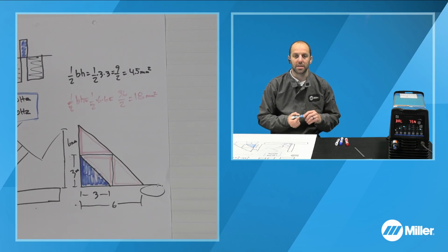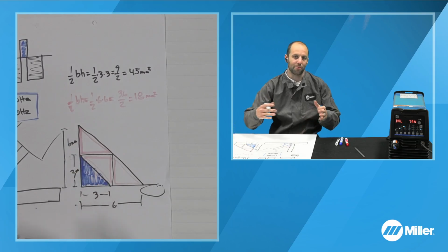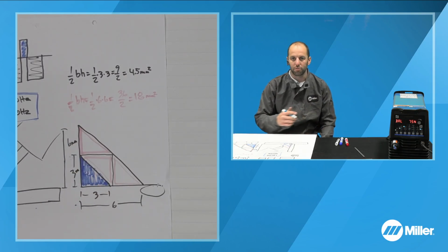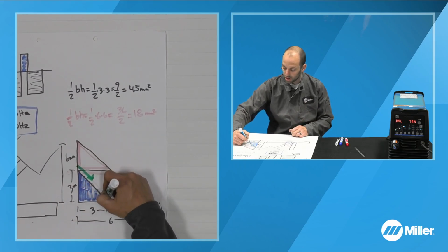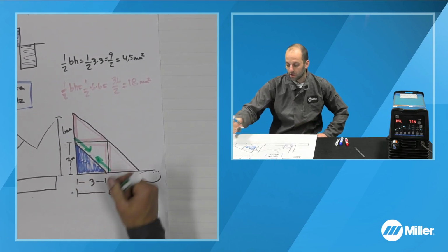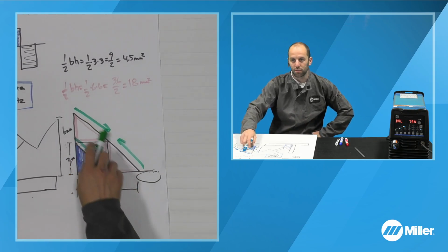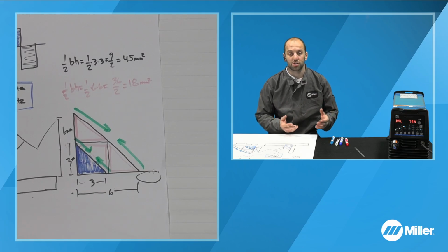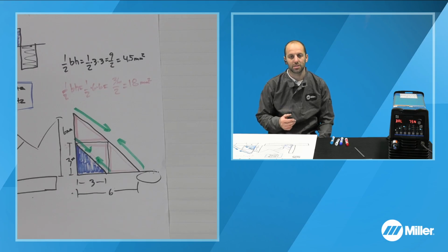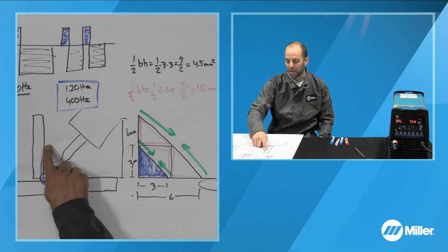The other thing that we want to consider is the actual distortion. As welders, we know that distortion is very critical in order to be successful. If we have to weld subsequent things onto it, or it has to fit into a fixture, or fit into a final application, you put your parts together, start welding it, stuff starts pulling, and that can cause problems. This is going to pull along the face of that weld. And you can see here, this one is about twice as much pull at the surface because of the distance here than if we do the smaller weld. That means twice as much distortion, twice as much straightening. Straightening and post-weld operations are, in many cases, a significant portion of a company's welding operations and labor spend. So as a manager, as an owner, even as a welder, that's why frequency is very important to making sure we get an appropriately sized weld.